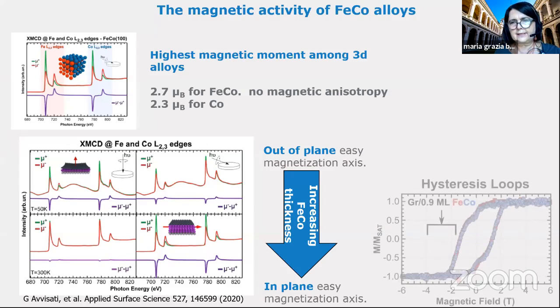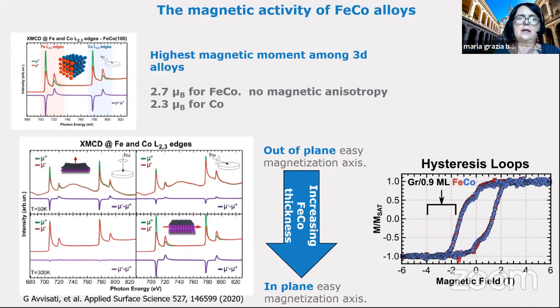So it's interesting, because now we can say, okay, I'm not sure that we really have iron and cobalt intercalated in a way that makes an alloy like this, but we could have a cluster of iron and a cluster of cobalt maybe. But we made a lot of measurements with low-energy photoemission and other techniques to better understand the intercalation process. In the end, I think one important result and a confirmation that we are really intercalating an iron and cobalt alloy, almost 50% iron, 50% cobalt, is the hysteresis loops: iron is the red one and cobalt is the blue one, and they are almost identical.